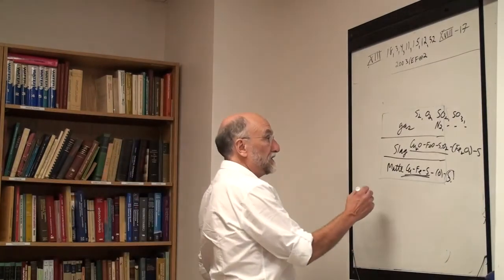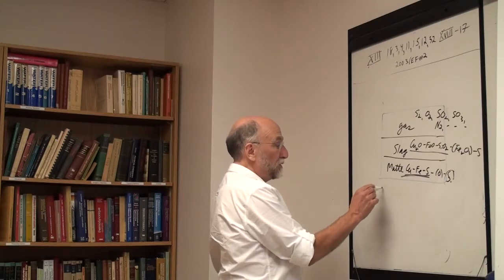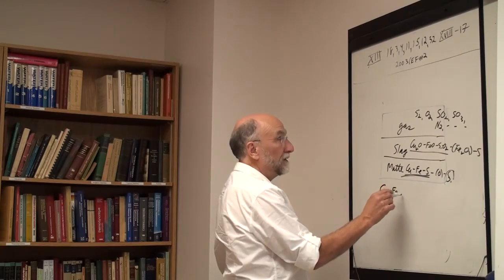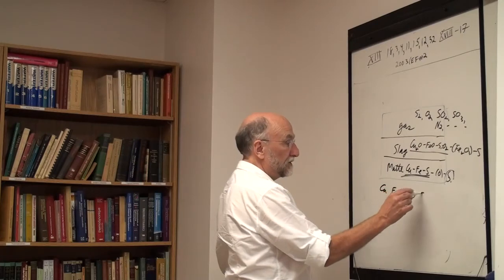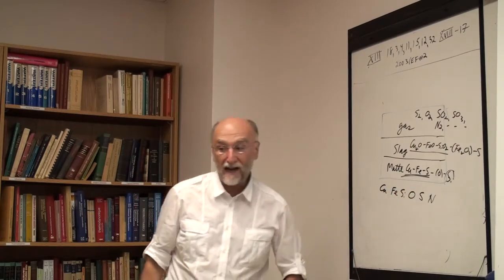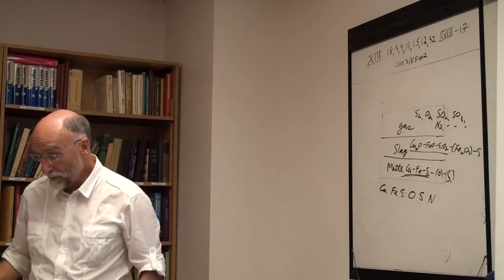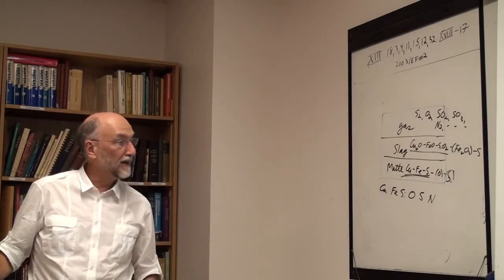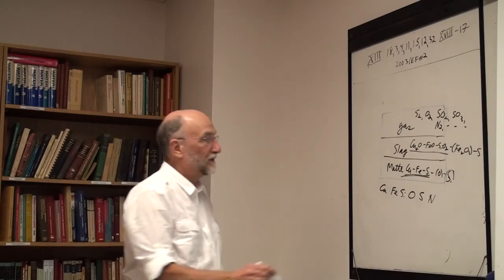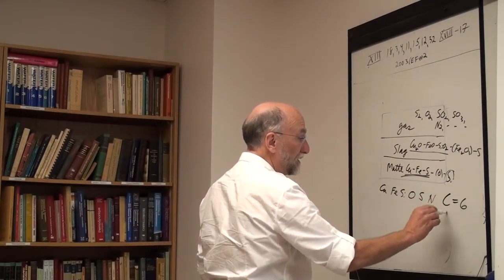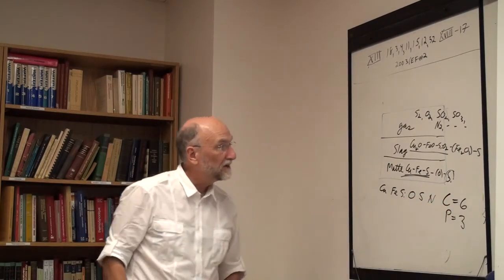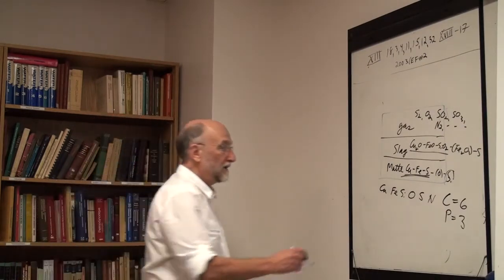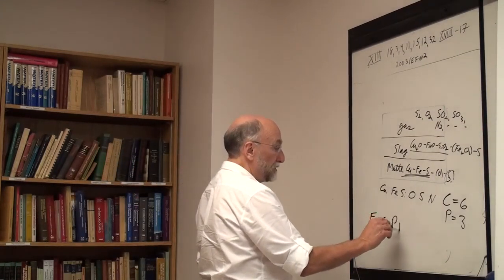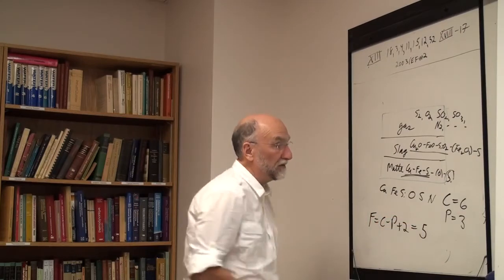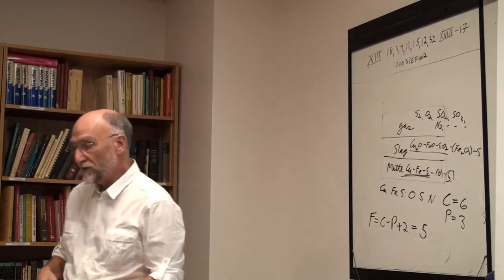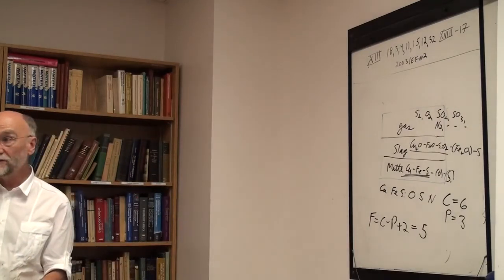Okay, so let's look at the composition. The components of the system would be copper, iron, silicon, oxygen, sulfur, nitrogen. You can't have more components than you have elements, so I'm going to go the whole hog and say I have a six component system. So the number of components equals 6. The number of phases is clearly 3: matte, slag, and gas. So the number of degrees of freedom is C minus P plus 2, which equals 5. So with those components and those 3 phases, I have 5 things that I can fix.